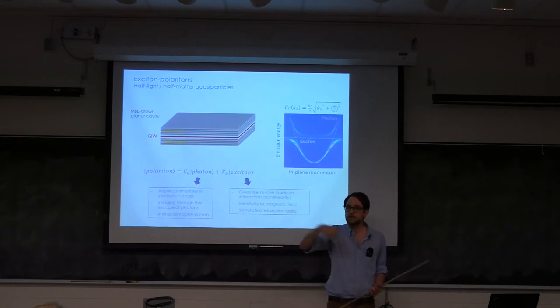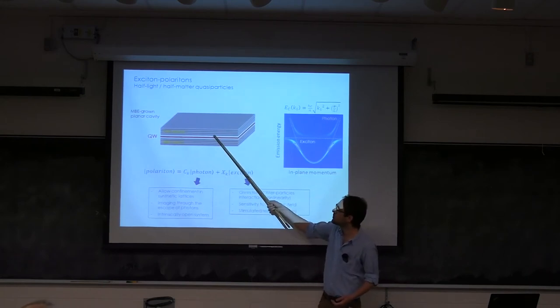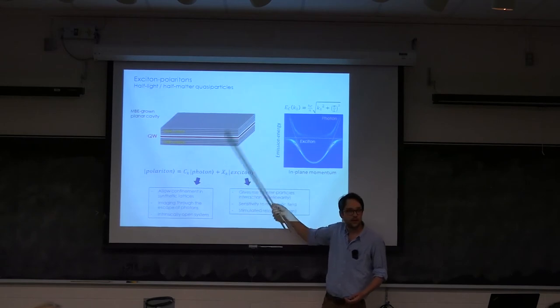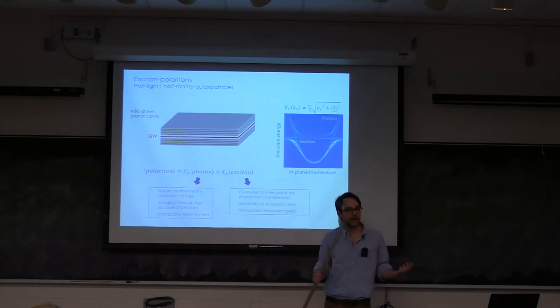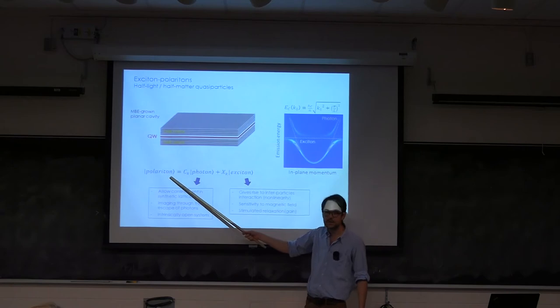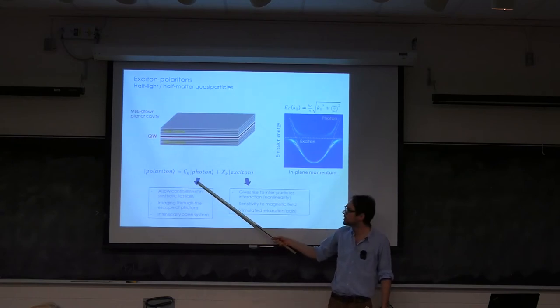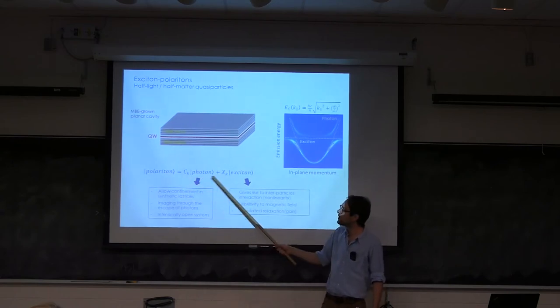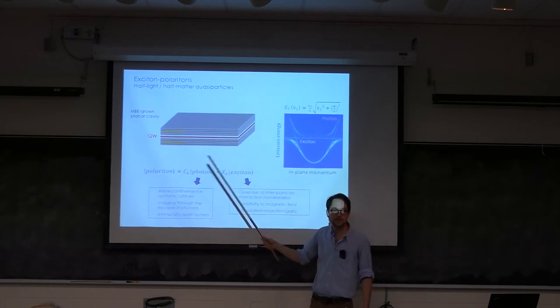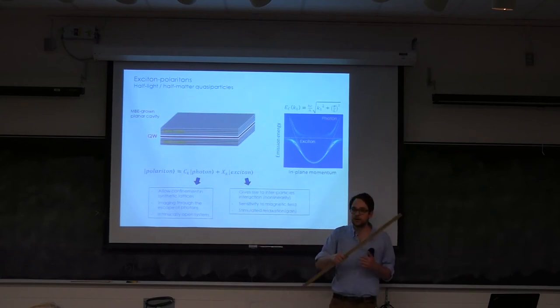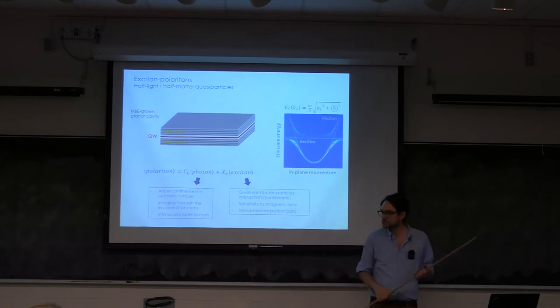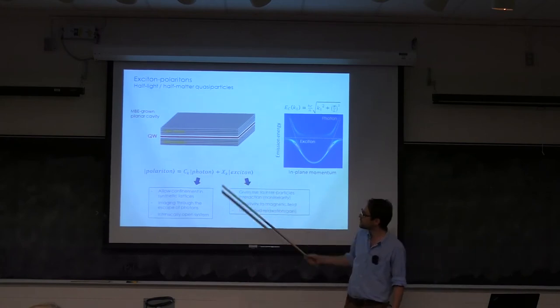And if the excitons absorb and re-emit and reabsorb the photon many times before the photon leaks outside of the cavity, that is to say, if the Rabi frequency is larger than the decay rate of the photon outside of the cavity, we enter a regime where we cannot distinguish whether we have photons or excitons. In fact, we have a new quasiparticle called a polariton, which is formed from the linear combination of a photon and an exciton with amplitudes that depend on the properties of your system. So how much in energy are your photons and excitons detuned?